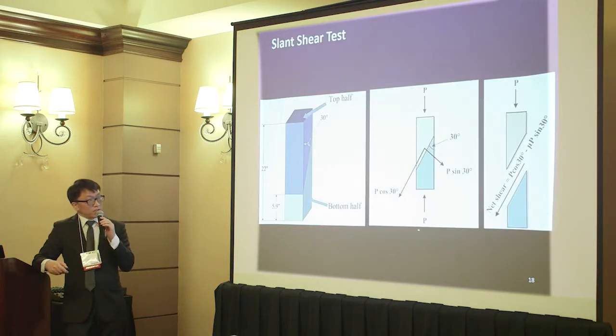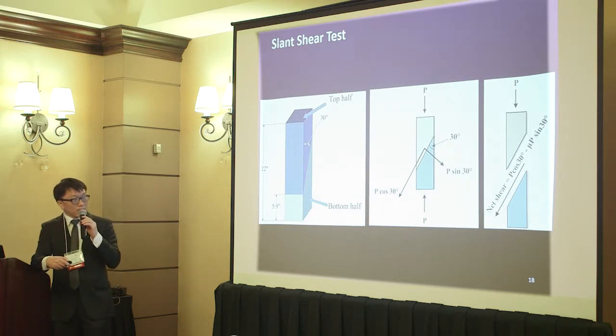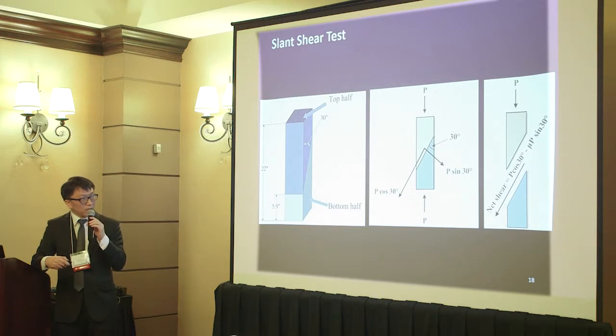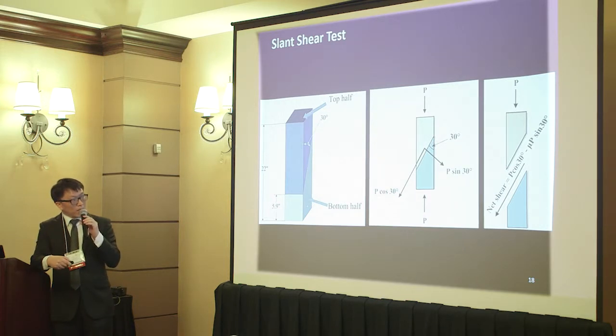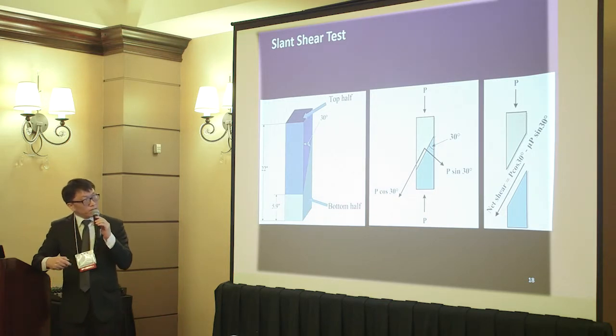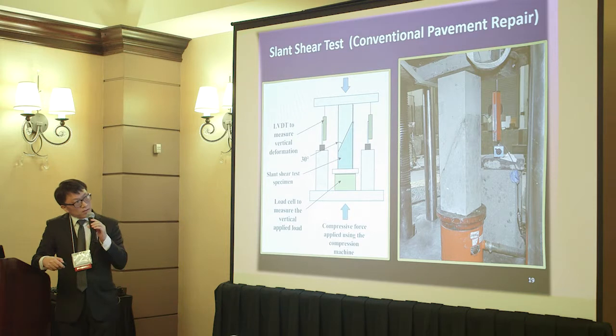To prove this concept, we did some testing in the lab using what they call slant shear testing. This is one of the most commonly used methods to check the shear strength of the interface between different materials. The bottom part represents the existing concrete, the upper one the new concrete, with loading applied on top. From mechanics, we know there will be shear force. At the same time, there is a force perpendicular to the surface that creates friction, and the friction will counteract some of the shear force. This doesn't represent the most realistic condition, but it gives a very quick way to understand the shear strength. This is the test setup at our lab.